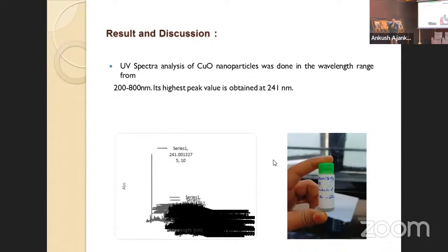After complete formation of the precipitate, we have to filter it again using filter paper, and it takes nearly a day for complete filtration, and the precipitate settles on the filter paper. We remove it and set it aside for drying. When the precipitate has completely dried, we collect it in a china dish, crush it into a fine powder, and collect it in a sample bottle. This is our final product, which is copper oxide.